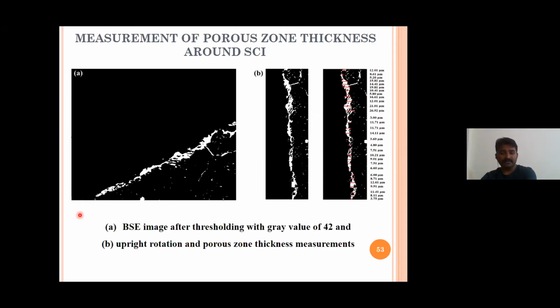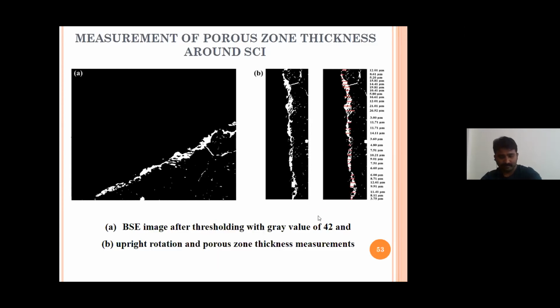So the A part is the BSE image after thresholding with a gray value of 42. You can threshold with 0, 10, 20, 40, even up to 56, right? Why have I selected only 42? In one of the papers we came to know that pores vary from 0 up to a maximum value of 42. Through that paper reference, we started thresholding with the value of 42, and the same was maintained for all the SEM images.